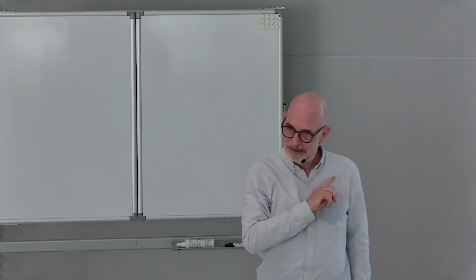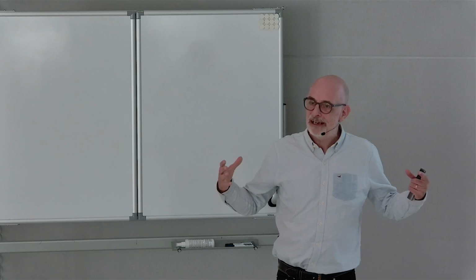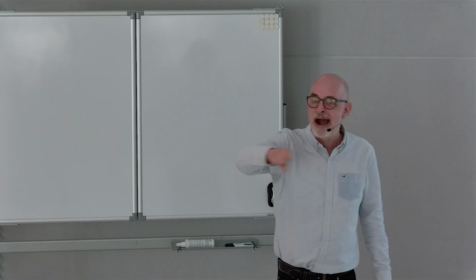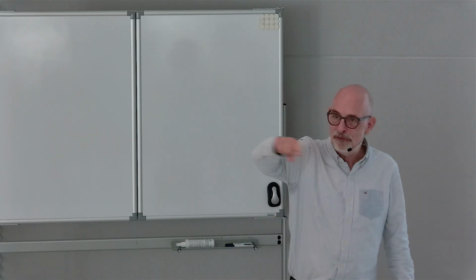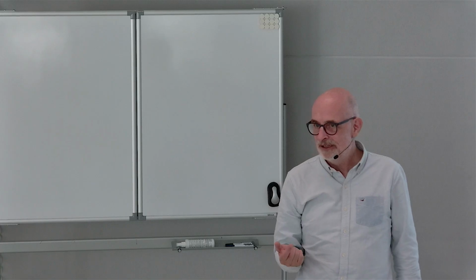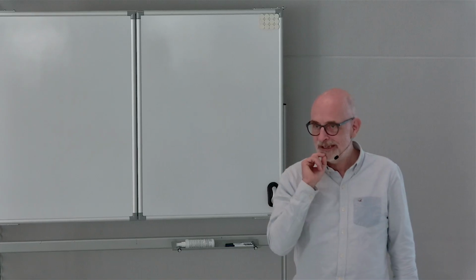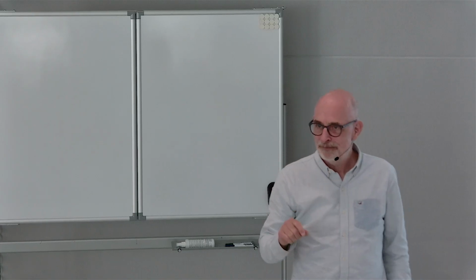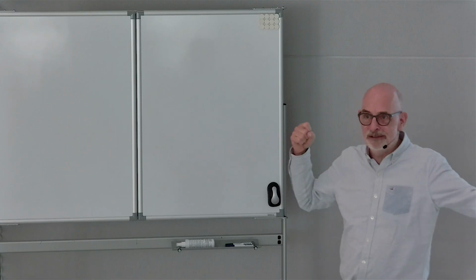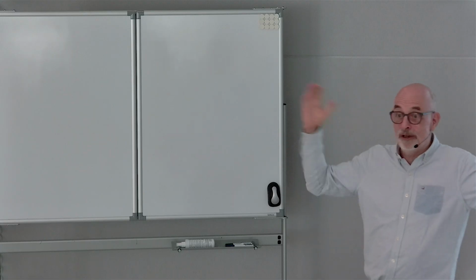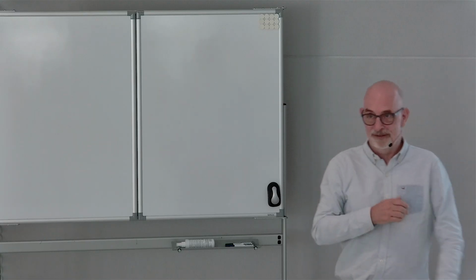And this particular device was relatively large, so the orbit was a micron. So the wave function saw very little of the edge. But if you build a quantum dot that way, it wouldn't work because it's just surrounded by dangling bonds of the graphene, and then the beauty of graphene is gone. Yeah, thanks.